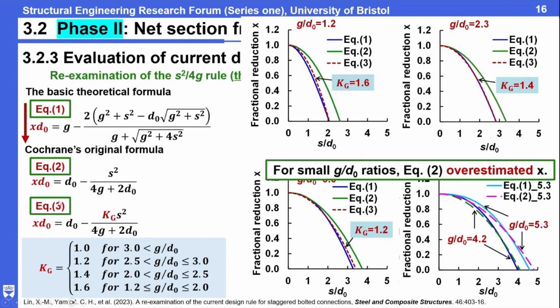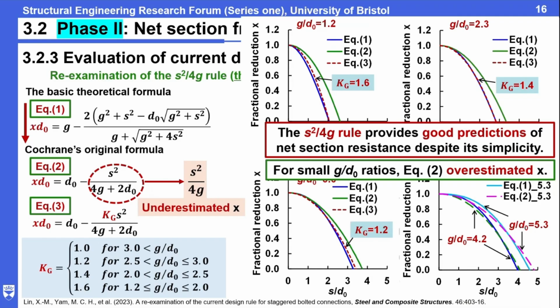But why, when we look at the test data, does the predicted value based on the s²/4g rule still seem like a good prediction? What's the reason? The x value has been overestimated already, so why is the result still okay? The reason behind it is here. Actually, the s²/4g rule just ignores this d0 term. If you remove this one, it means the x value is underestimated already. The overestimation and underestimation cancel out. So that's why the current s²/4g rule can still provide a good prediction. But the reason behind it, no one has mentioned before, and we looked further to find that out.